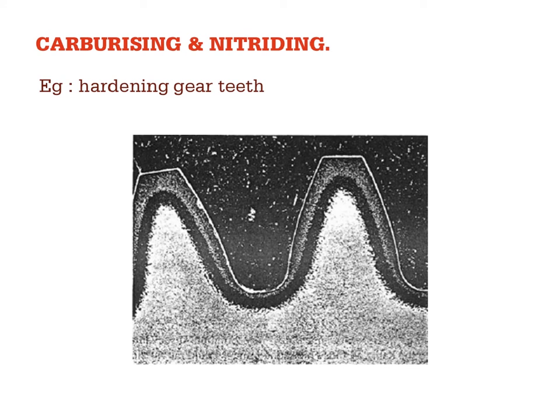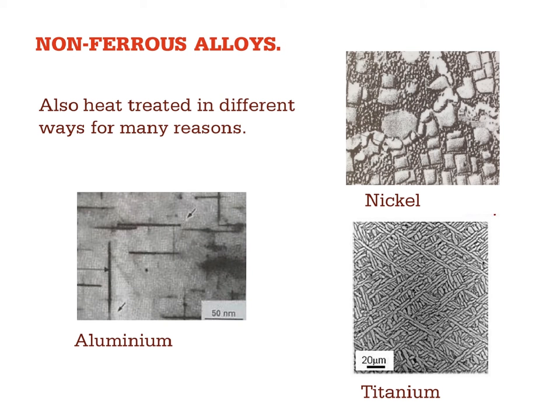And the final example of heat treatment for steels is, normally heat treatment is carried out for the bulk of the product, and it's done in a vacuum or in air. If you heat treat in a carbon or nitrogen rich atmosphere and heat the component up to maybe 600 or 700 degrees C in, for example, methane or ammonia, which would break down to release carbon or nitrogen, that then diffuses into the surface layers, and this image here is of the teeth of a gear wheel. By diffusing the carbon and nitrogen into the surface layers, we have a very hard outer surface, which is wear resistant, but the central core is very tough. So that's another form of heat treatment.